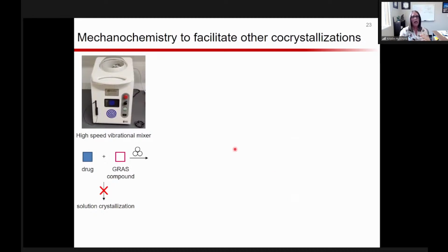What we are now doing, it's really preliminary, so I'm not going to show specific structures, but we've now taken some different drug molecules, not bezafibrate, and we are co-crystallizing those with generally regarded as safe compounds, so again on the FDA's list. And we've chosen a system where both of these are actually solids, they're not liquids, but when you do solution crystallization, they just do not co-crystallize. And we've chosen about 4 different drugs that fall into the same class and a couple different GRAS compounds. So solution methods just fail across the board and typically give us crystals of the single components independently rather than a co-crystal.